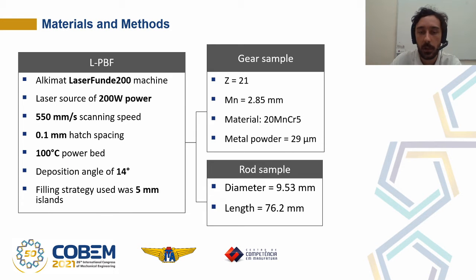There are 3 specimens of additive manufacturing made with laser powder bed fusion technology, which are 2 rods and 1 gear. The spur gear used for the measurement has 21 teeth, 2.85 millimeters of normal module, 20 manganese chromium 5 is the material, and the metal powder has a medium size of 29 micrometers. The 2 rod samples have a diameter of 9.53 millimeters and a length of 76.2 millimeters.